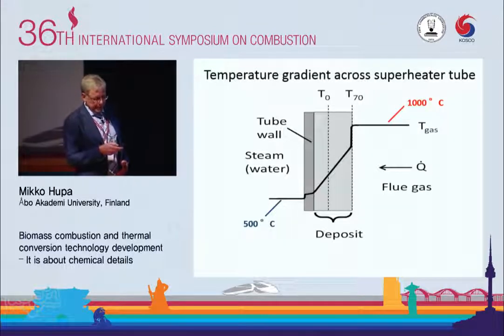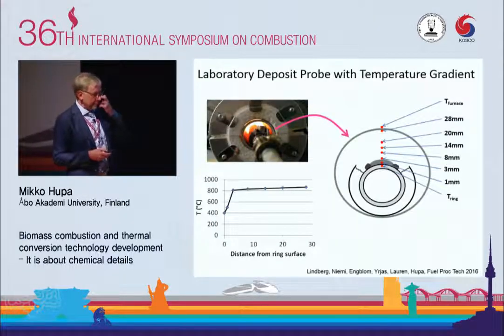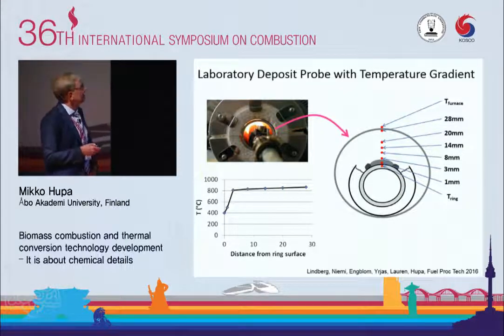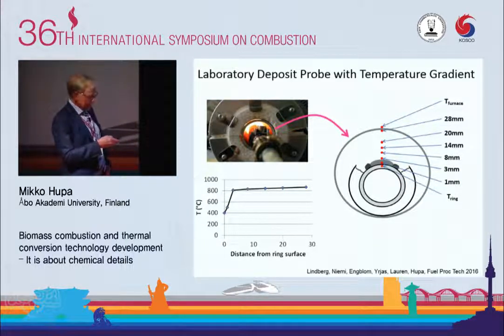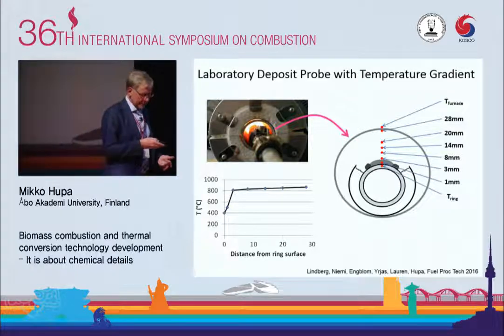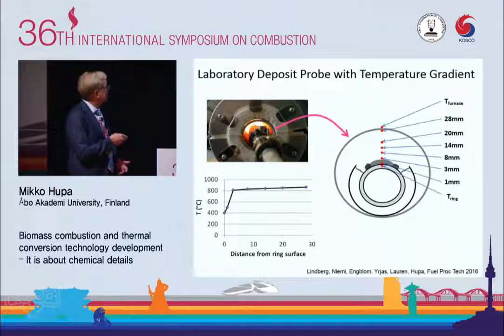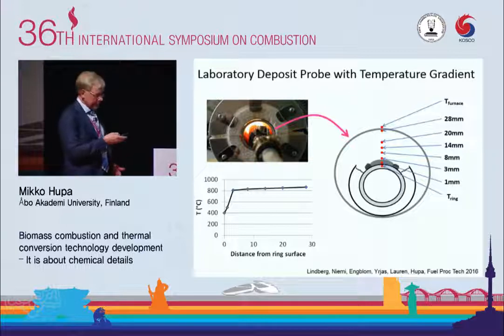Finally, recently we were able to produce such a gradient also in the laboratory. This is not a very clear picture, but the idea is we have a cooled pipe where inside temperature was 500 degrees, for instance, and then we can put our deposit sample here. But we have to cover the rest of the tube for heat transfer reasons. And then if we have only that part open and we have a hot furnace around, we can create something very similar. And we can have a gradient inside that deposit.